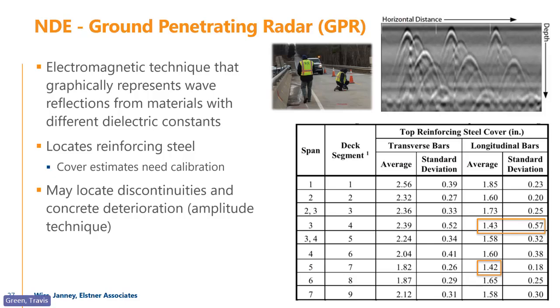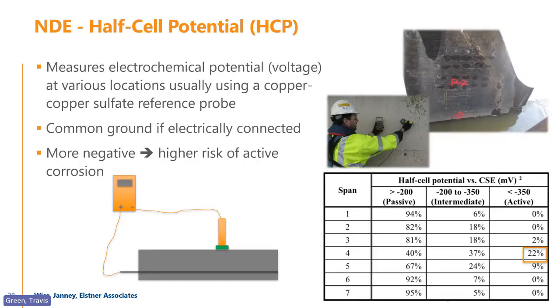We did ground penetrating radar work to look at cover. Obviously this particular item feeds right into the service life model, right? Because we need to know where the bars are to get some kind of normal distribution curve on reinforcing steel position. And so this is what it was intended to do. We then came through and did some half cell potential measurement. So this is measuring whether there's a high likelihood of ongoing corrosion, right? Generally speaking, the more negative you are, the more likely there is for corrosion to be there.